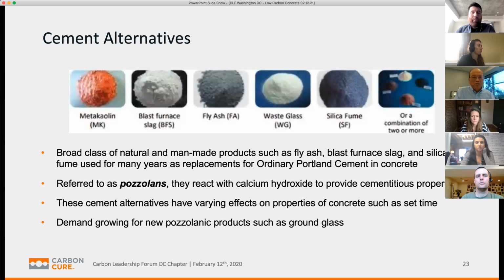So I spoke a little bit about fly ash and slag, and I just wanted to talk a little bit further about some of the cement alternatives out there. Looking here, you can see all these very nicely colored, nicely hued powders. So anybody who gets excited about chemistry, this is all the good stuff. You can see some of the names up there, the typical ones: fly ash, so FA, furnace slag, silica fume, others that are used. But there are also emerging new materials that are being investigated that could do the same thing. What these materials do is basically act as a substitute for cement. So again, they typically replace it at a 1-to-1 ratio in the mix, and then you would see a corresponding reduction in cement.